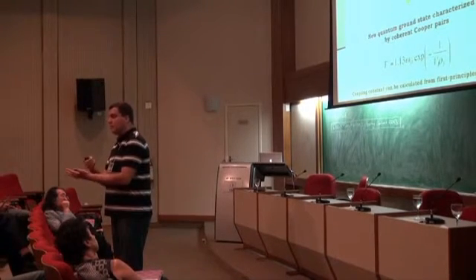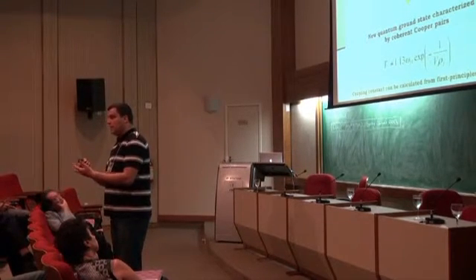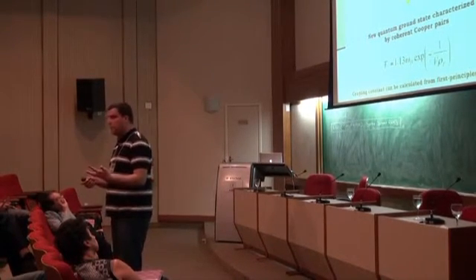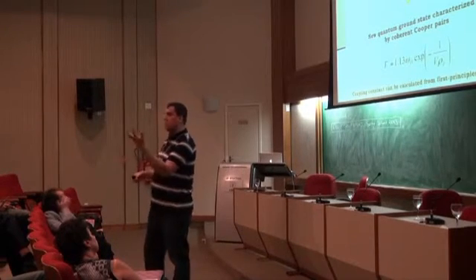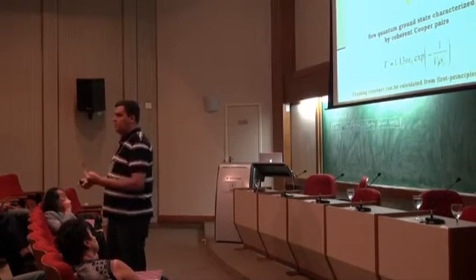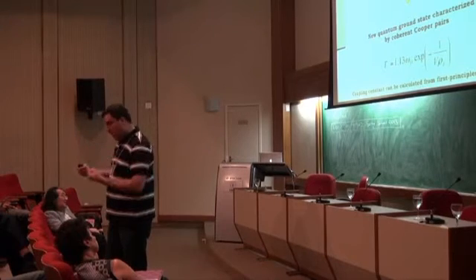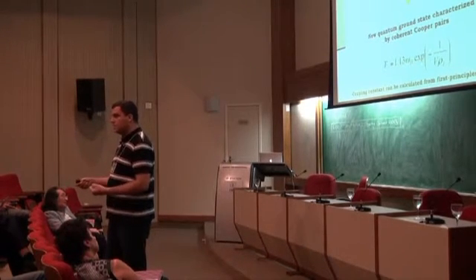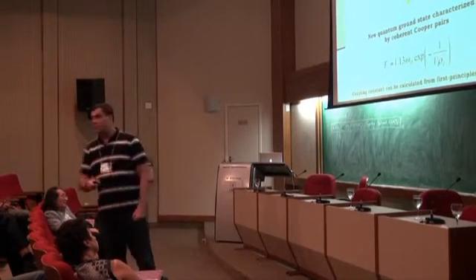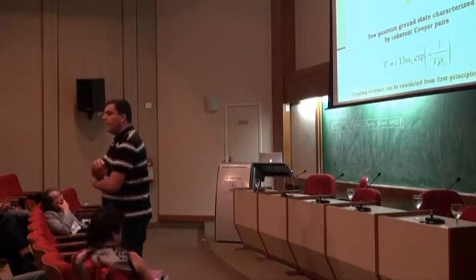And the electrons and the lattice become much more strongly coupled because of the existence of soft modes. And that leads to the highest Tc. So applying pressure is just a way of changing the lattice, deforming the lattice, and trying to bring this coupling constant up or down.